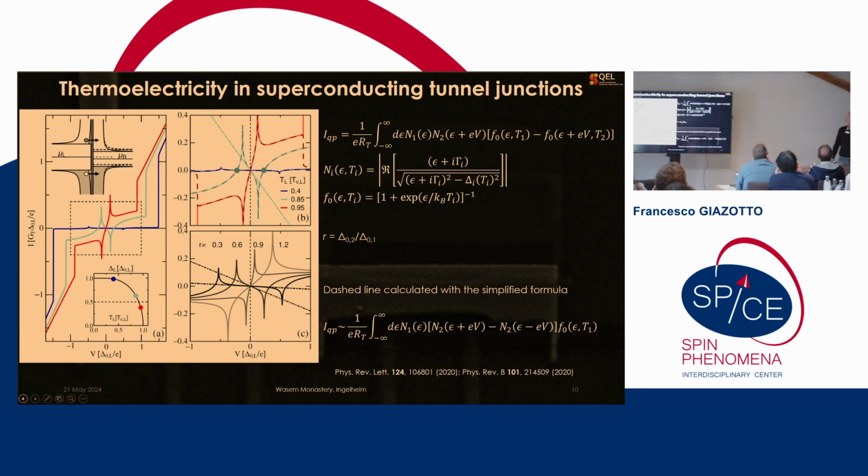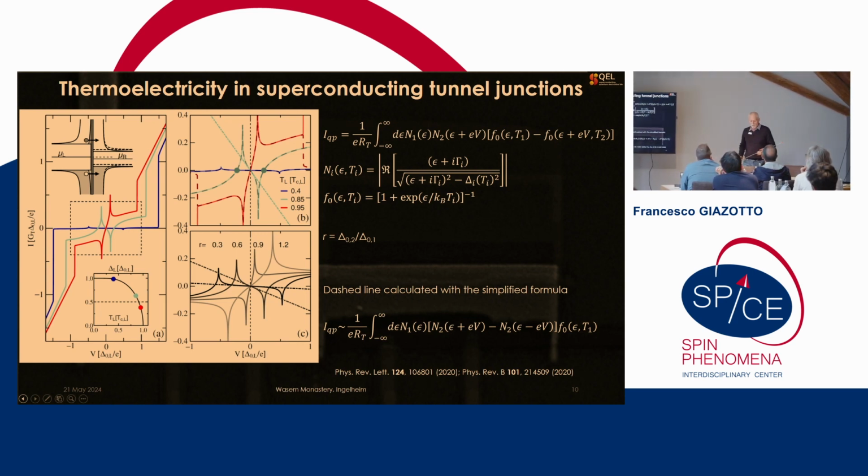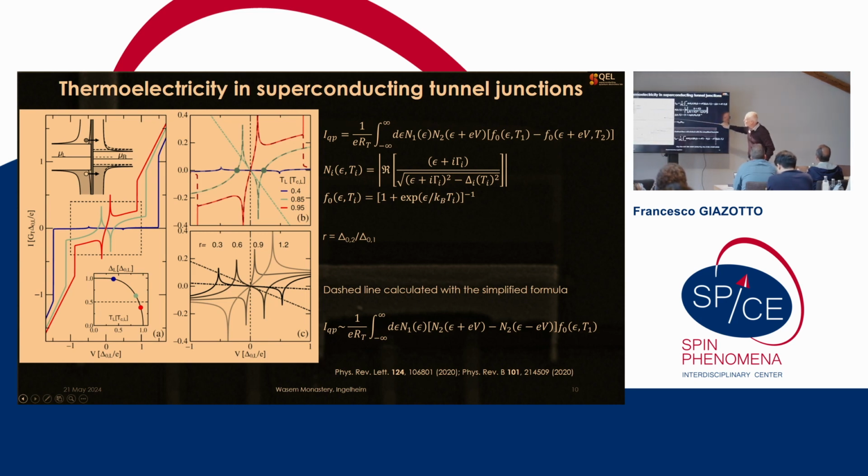Well, it's a good question. We use this because I am a trivial experimentalist. For me, it's a very phenomenological way to express non-idealities in the junction. If we consider non-ideal behavior in the junction in terms of partial Andreev reflection, the larger is gamma, the worse is the response, because it tends to increase the conductance. So it tends to mask this effect, like the supercurrent itself. This will create a parallel channel, so it will increase the current in the system, okay?